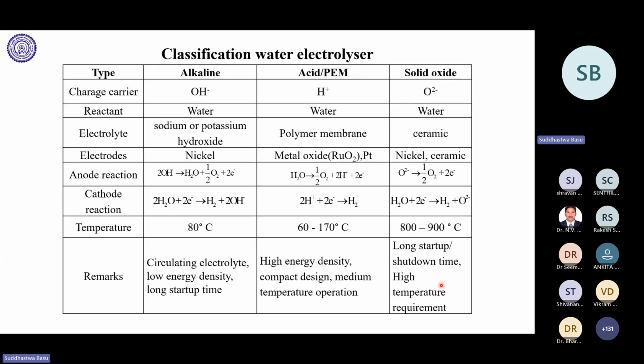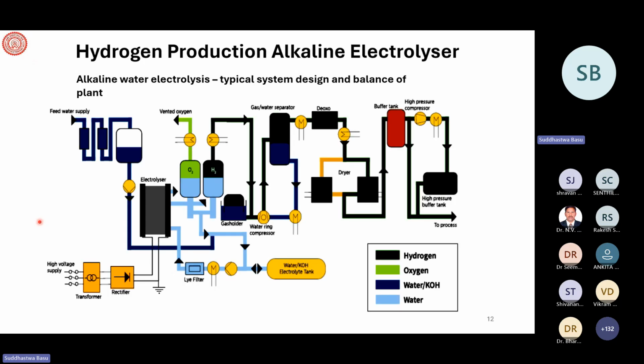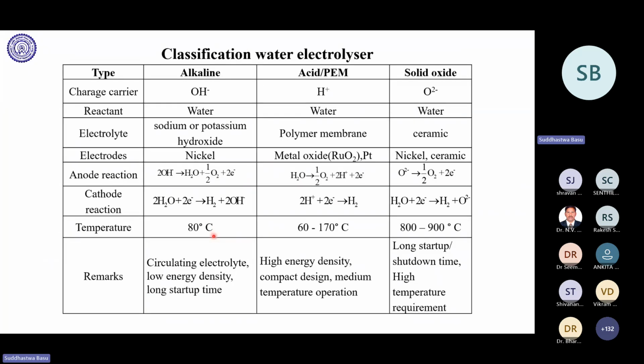So it has a long startup time, and shutdown time is also long. High temperature operation is not so easy, 800 to 900 degrees Celsius. This is a relatively lower temperature, 60 to 170 degrees Celsius. In acid or PEM electrolysis, there is high energy density, compact design, and medium temperature operation. Okay, 60 to 170 degrees Celsius. And this is 80 degrees Celsius, alkaline electrolyzer, circulating electrolyte. We circulate because the electrolyte is circulated, which we talked about, the light blue color. Okay. So this is the difference between alkaline, acid and solid oxide electrolyzers.